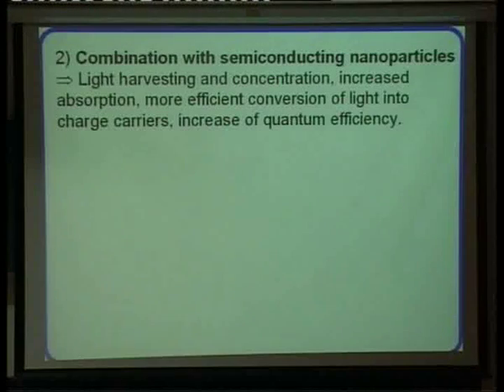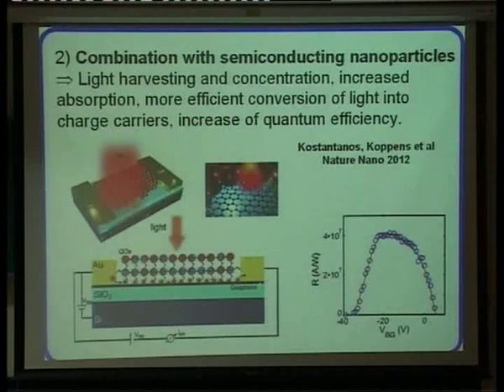The other option is to combine graphene with semiconducting nanoparticles. In this case, those do the light absorption, and they create electron-hole pairs, and then graphene helps extract them from the sample. And again, there are pretty amazing results that were produced in 2012, where responsivity is now about 10 to the 9 amperes per watt. 10 to the 9 amperes per watt is basically close to single photon detection, so a new field of research is being opened there as well.